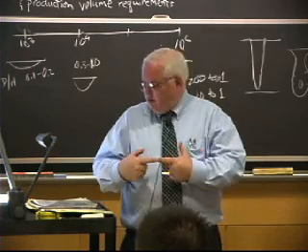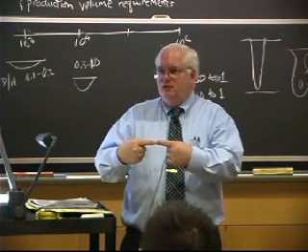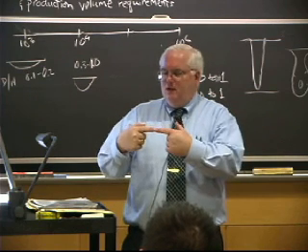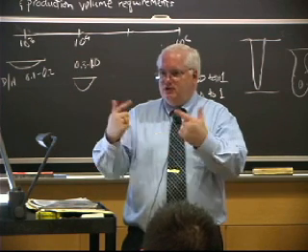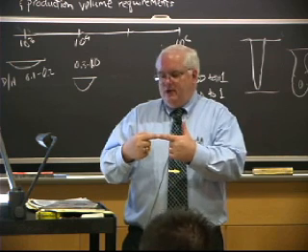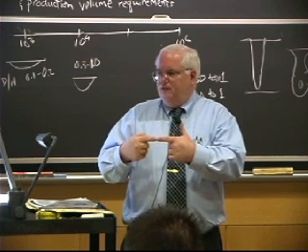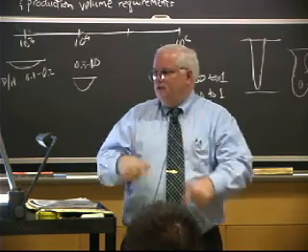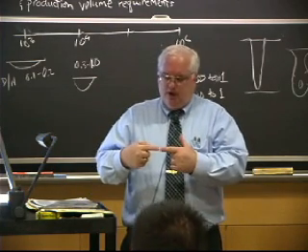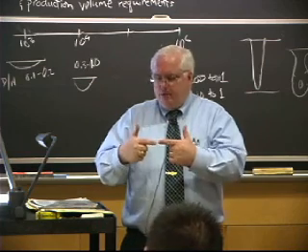Just a DC current, and in fact, people will weld rods together in a steel mill or somewhere. You just butt them together, and at the interface you have electrical resistance, a higher resistance than in the bulk of the material, and you pass a few thousand amps, or maybe 5,000 or 10,000, depending on the diameter of the rod, for a few seconds, and the thing will heat up there, and you just kind of forge the stuff together. It's basically a diffusion, or a forge weld. It's a solid state weld. You haven't melted metal necessarily.